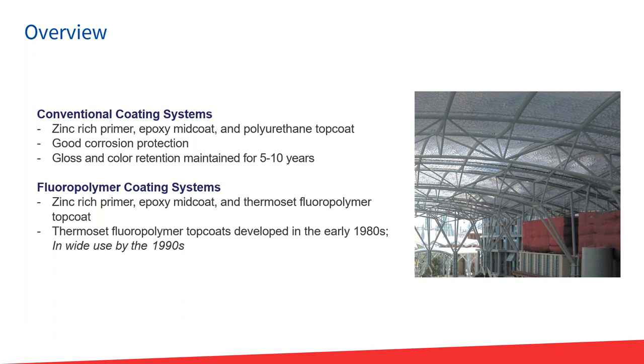For example, in a bridge application, especially a large steel bridge over a major body of salty water, those bridges are oftentimes coated with a three-coat system, starting with a zinc-rich primer, then an epoxy mid-coat, and then some type of top coat. For high-performance systems, that's usually a polyurethane top coat and possibly even a polysiloxane top coat. These systems offer very good corrosion protection, primarily due to that zinc-rich primer. And the top coat is really where you're getting your color and your gloss retention.